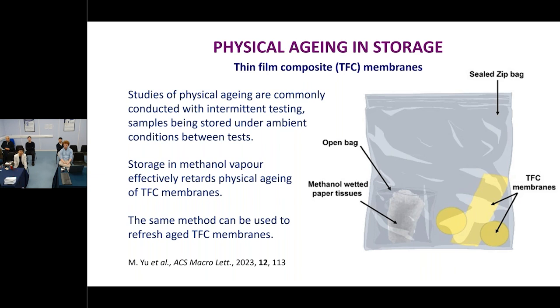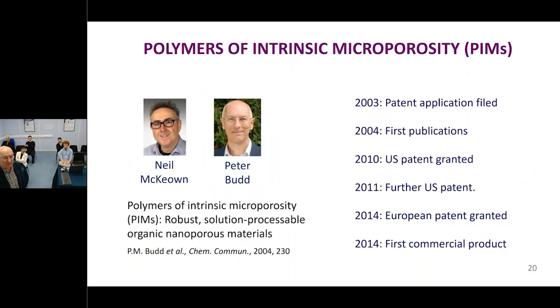In real life, of course, a membrane is used with continuous permeation. And what happens under those circumstances may be very different to what happens when the membrane is sat in the drawer. And we need a lot more data, we've got very little data actually about what happens under ongoing conditions of use. So that's an area where we need a lot more information. But what we can say is that actually how you store things can make an enormous difference. And so one thing we've been playing with is storing in a methanol vapor atmosphere rather than just in air, which has quite a reasonable effect.